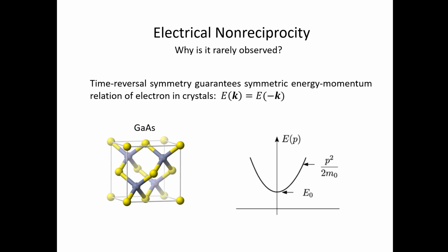The absence of the second order nonlinearity in most conventional materials actually has a deep reason. That's because in addition to inversion symmetry, time reversal symmetry also relates states with opposite momentum. Under time reversal, the electrons' momentum gets reversed and the current gets reversed. So if we look at the energy momentum relation for electrons in solids, in conventional materials such as silicon or gallium arsenide, or in graphene, as Pablo said earlier, this relation always holds: the energy momentum relation is an even function. E of k is equal to E of minus k.